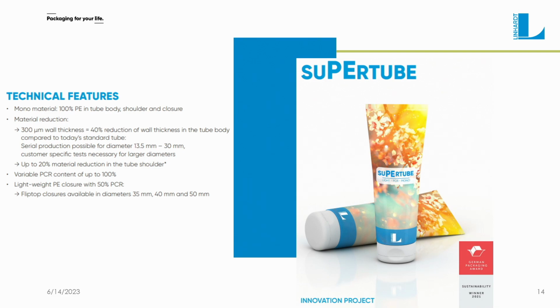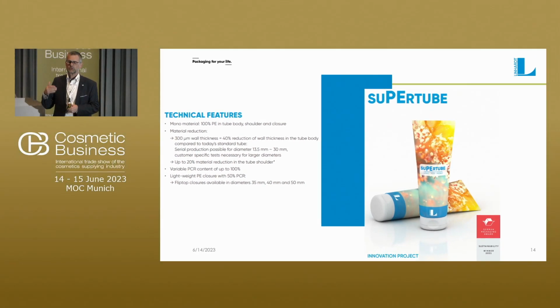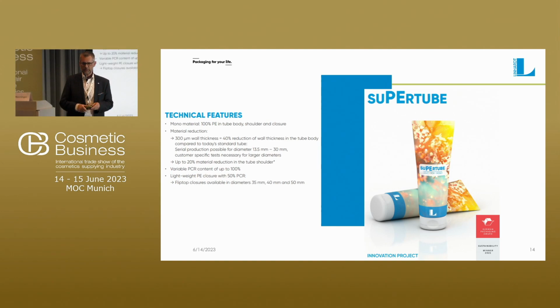We have a lightweight PE closure, which means we have a mono PE tube and a weight-reduced closure, which has a 50% PCR content. Back when we won the award, now we're working towards offering 100% PCR in the closure, and also for flip-top closures. What you can see here is we tried to bring reduce, replace, recycle together in the super tube to actually meet all those requirements in one single tube.